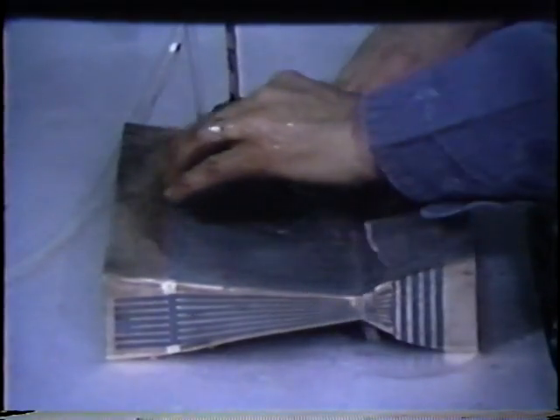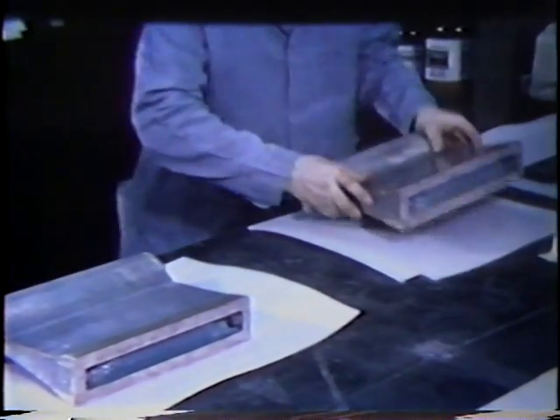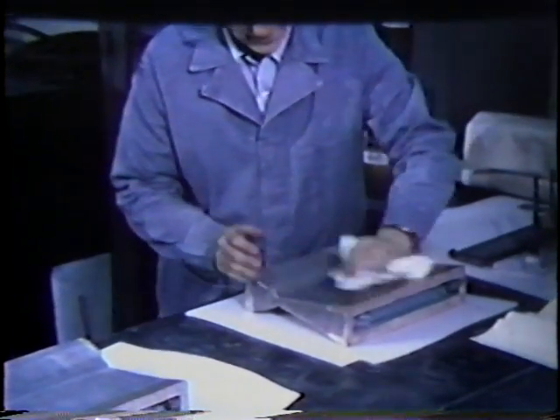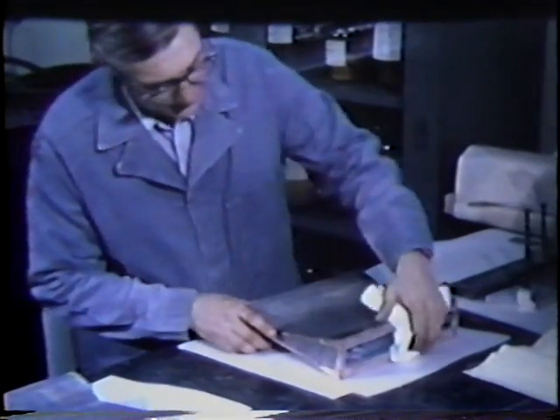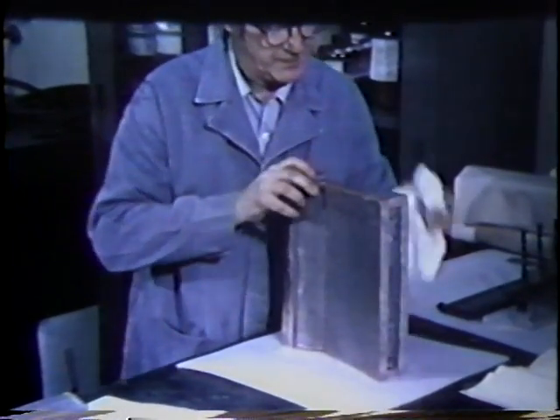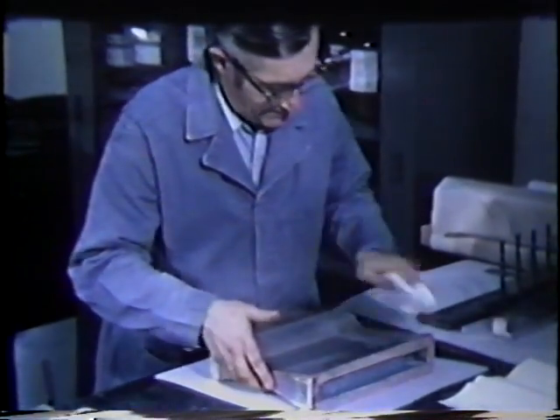Rigidex, a material specifically developed for use as a filler in the coolant passages during electroforming and manufacturing processes, was selected for use. The cast segment design contains relatively small coolant passages, which introduce the possibility of a restriction or clogging from foreign material. The reduced coolant flow in the restricted channel could result in wall overheating. To avoid this possibility, the Rigidex is left in the liner throughout subsequent machining operations.